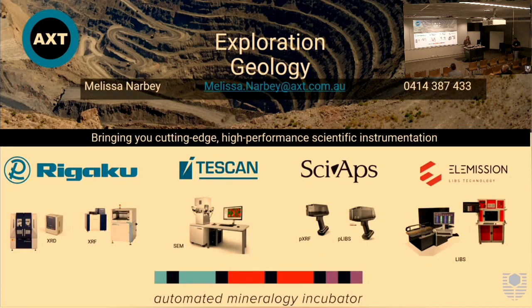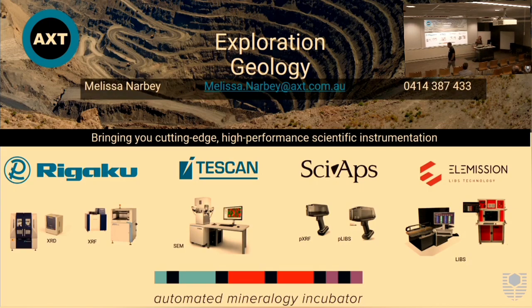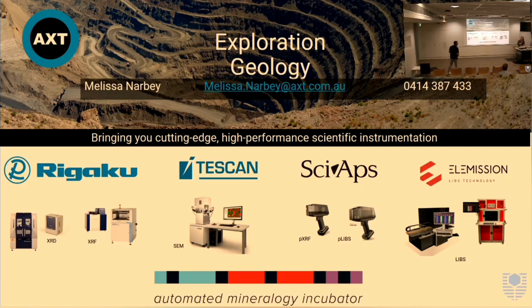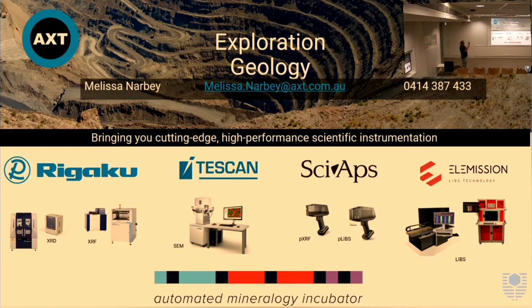Chip trays compared to the cores, do they have to do anything different, like because of the interaction with the surfaces? So as long as the height is within 6 millimetres, it can analyse chip tray. The particles really need to be greater than 1 mil, ideally 2 mil, because if they're smaller than that, you get this laser matter interaction.